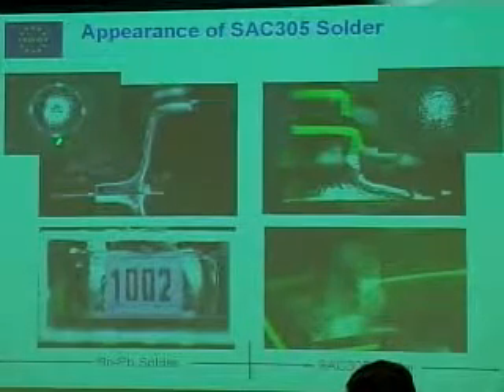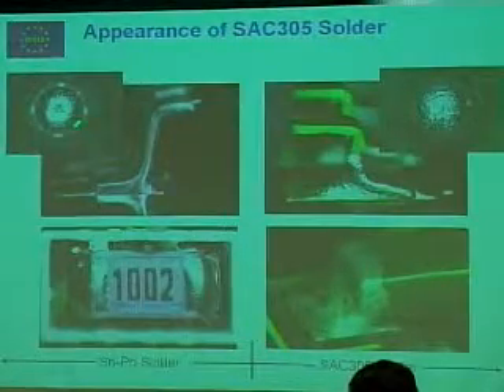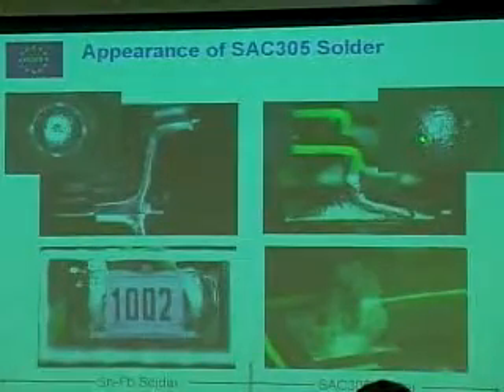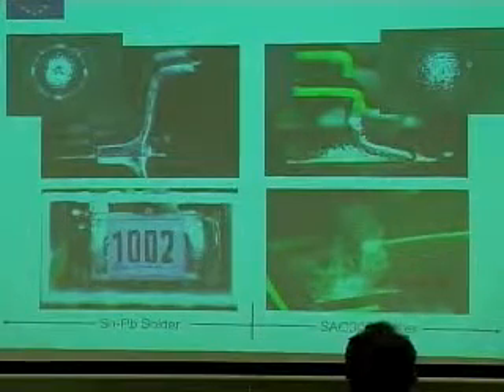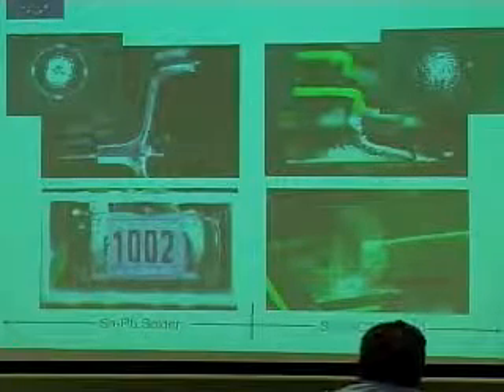Here's just a solder ball, nothing attached to it except it's sitting on a pad. Lead tin, and you get a rougher surface. This is actually pretty good. But some of them look actually worse than this. But the SAC solder looks rougher. You actually get microcavities on the surface of these balls as they cool.